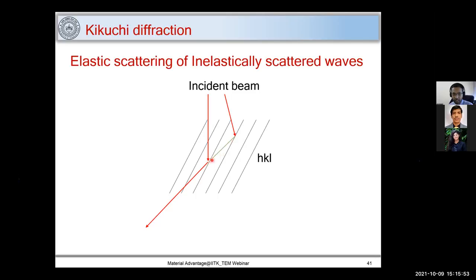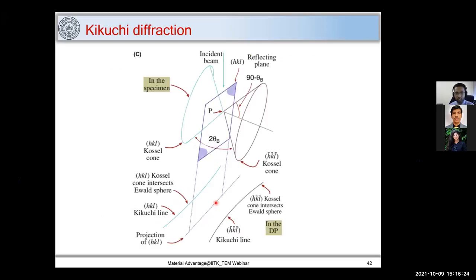Now this inelastically scattered wave will go through elastic scattering. That means there will be no loss of energy here, and you get diffraction like this. So you get a high intensity here and a deficient intensity, because in this case you have 2 incidences where one incidence was of inelastic scatter. So there was a loss of energy. So you will have higher intensity in this line, and you have deficient intensity in this line. And this is what we call Kikuchi diffraction.